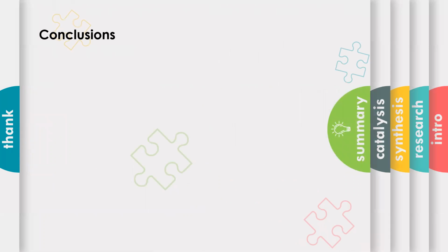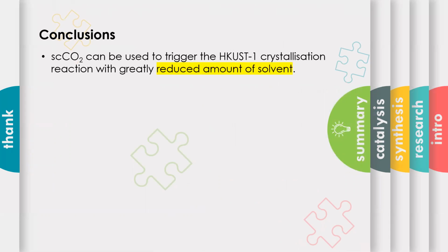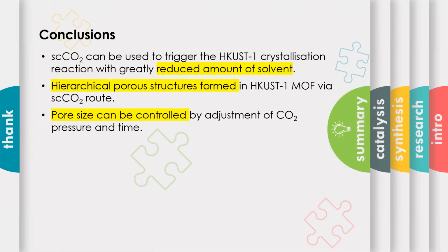To conclude, we have demonstrated that supercritical CO2 has some advantages in MOF synthesis, for example, an increase in MOF formation rate and a decrease in the amount of solvent. This synthetic method can provide another factor to control particle size and porosity and provides an excellent route to synthesize MOFs with hierarchical structures.